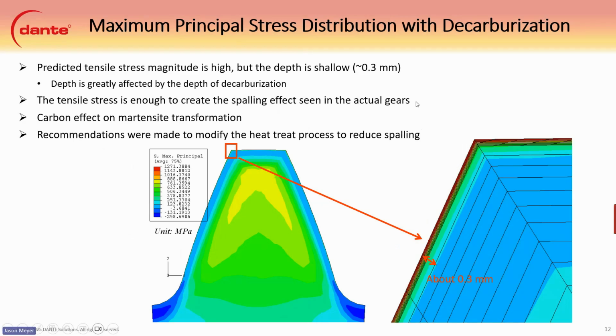So when we run the stress model, the maximum principal stress distribution with the decarburization model, the predicted stress magnitude is very high. You can see the peak is at 1200 MPa, but the depth is very shallow. It's only about 0.3 millimeters. And this depth is greatly affected by the depth of decarburization. So, obviously, longer decarb would give you less carbon near the surface, and so it can give you higher tensile stresses. This tensile stress is enough to cause the spalling effect that we see in the actual gears.